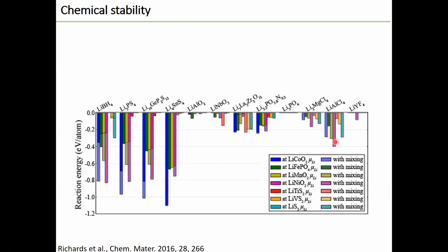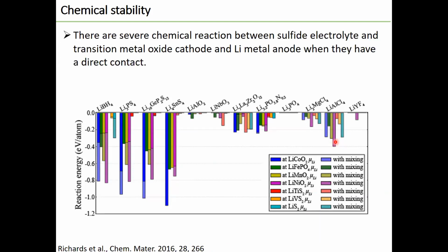Another big challenge is the chemical stability of sulfide electrolyte against high voltage transition metal cathode and lithium metal anode. The reaction energy between various cathodes and sulfide electrolyte is much higher than with other electrolytes. To solve this problem, it is necessary to insulate the cathode from the sulfide electrolyte. Many works have proved that the reaction between sulfide electrolyte and lithium metal is also very drastic.